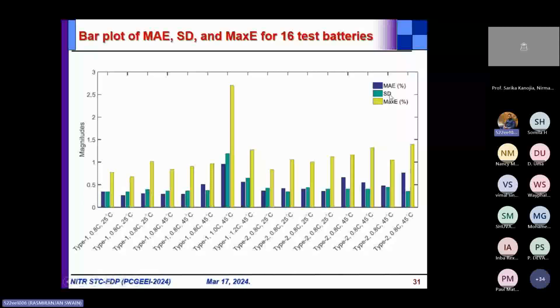This is the standard deviation, this is the maximum error. So mean absolute error and maximum error have been represented in terms of percentage. Here you see all types of batteries, type 1, type 2, and various conditions, like different rates of charging and temperature, shown here. In the majority of cases, we have achieved mean absolute error less than 1%, and the standard deviation was below 0.7. You can see one or two isolated cases where the error is a bit high.